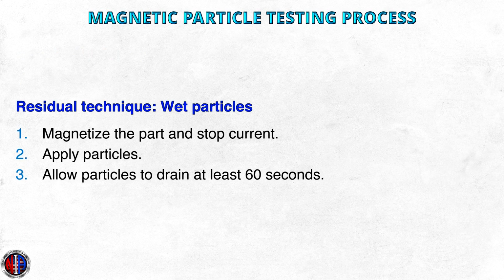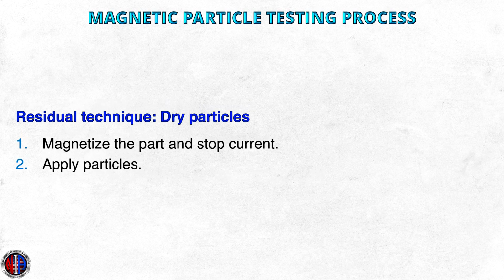The residual technique for wet particles is very simple. 1. We magnetize the part and then stop the current. 2. We apply particles. Then 3. We allow the particles to drain for at least 60 seconds. The residual technique for dry particles is equally simple. 1. We magnetize the part and then stop the current. 2. We apply our particles.